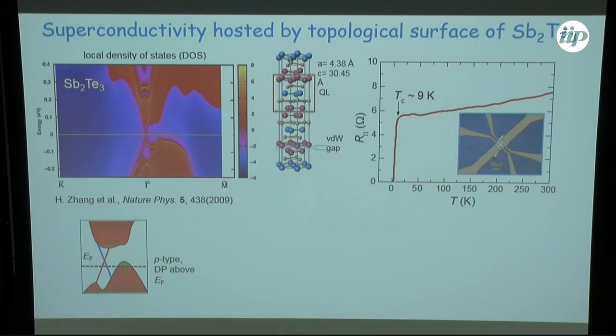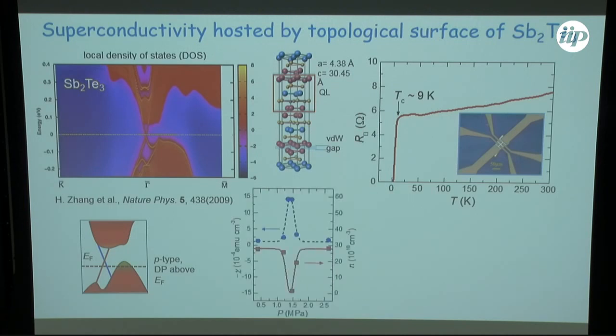However, the puzzle started later, because when we looked at the carrier density, on this axis is the synthesis pressure, we found a very non-monotonic behavior with the synthesis pressure, where the carrier density goes down by 3 orders of magnitude. It goes from 10 to the 20 to 10 to the 17 per cubic centimeter for bulk. At the same time, in this region, the diamagnetic signal just shoots up tremendously.